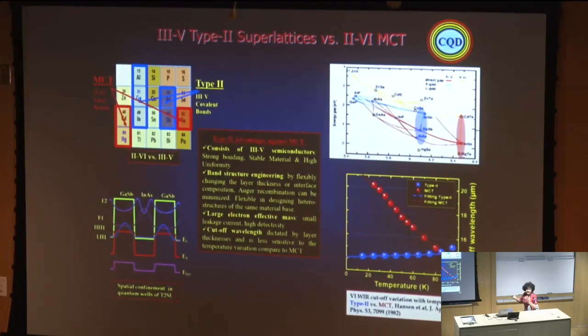On the other hand, mercury is a big atom. When you come to the 8-9 micron, the energy gap is small, so the effective mass decreases. And the effective mass is related to the dark current of the detector. When the effective mass is small, the dark current is high. And on the other hand, for this material, when we go to the long wavelength, in order to go to different wavelengths, the change of the composition variation is very rapid. So it's very hard to have great uniformity, and there is no substrate. So for any substrate, we have to put at least 10 micron of buffer. So the conclusion is, this is excellent, but with all of these problems.